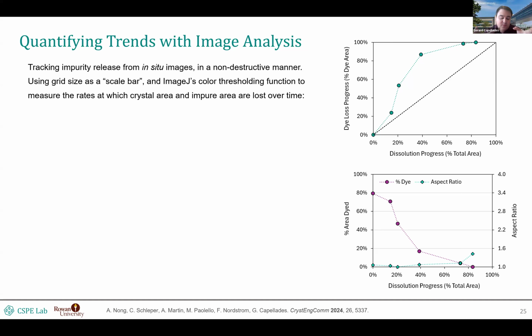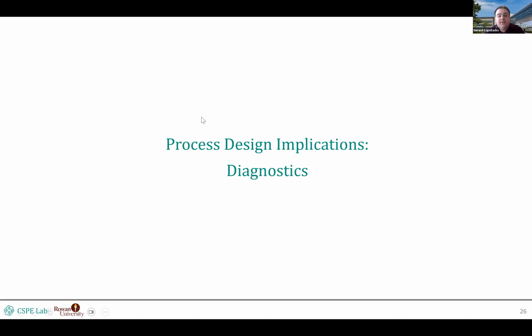I think we've been misdiagnosing solid solutions, and that's why they've been absent from the literature, because we tend to think that if I dissolve 20% of my material and most of the impurity comes out, it must be at the surface. It must have precipitated as a film on top of the surface, or attached itself by surface adsorption. But it doesn't have to be that way. It could be lattice incorporation that's being masked like this.